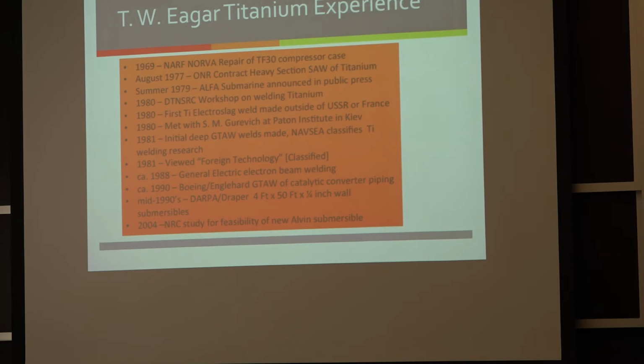And then I had to go watch the guy weld it up, which wasn't too hard, it's not too hard to weld titanium for a thin sheet. And then I had to watch the guy peen it to see if he stress relieved it properly. There was absolutely no reproducibility whatsoever on these test strips for the residual stress relieving, okay? But we had to get that engine out, right?